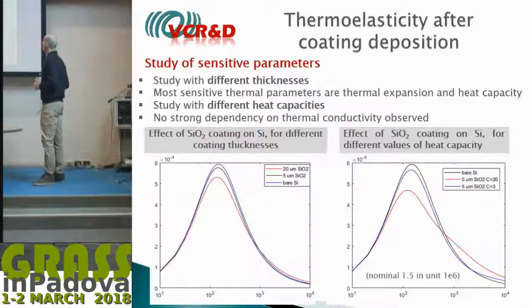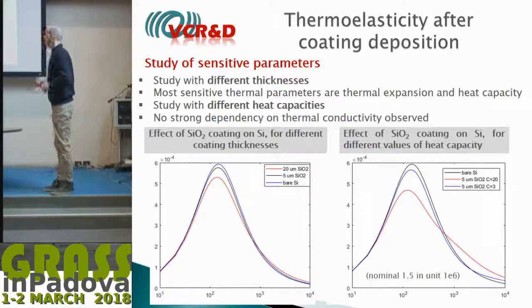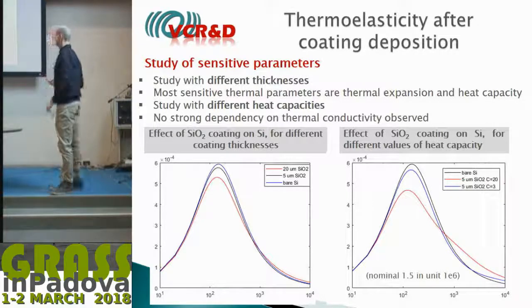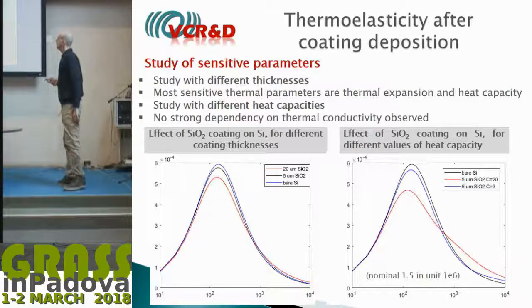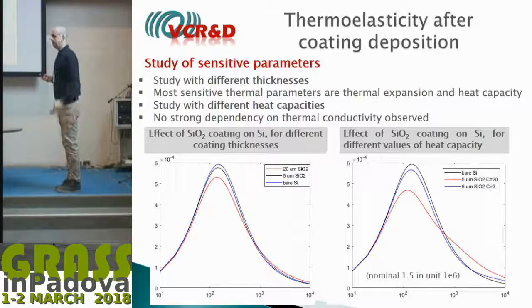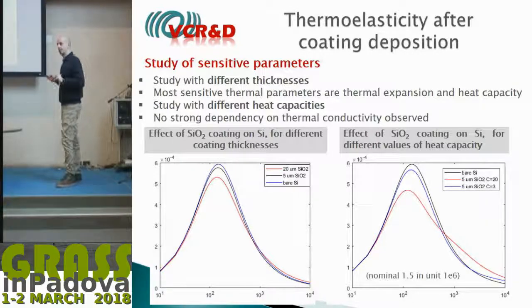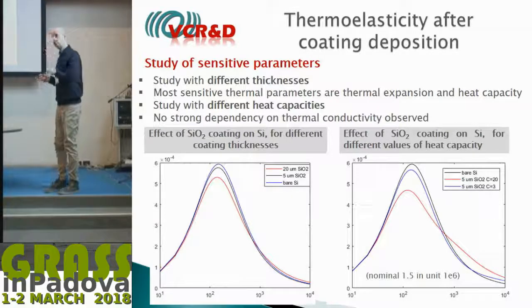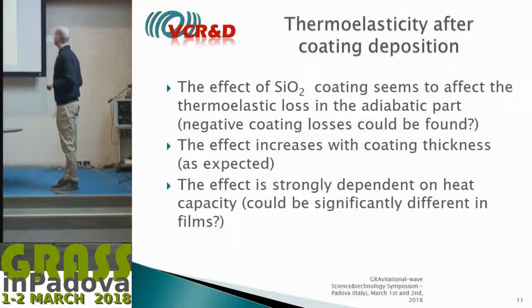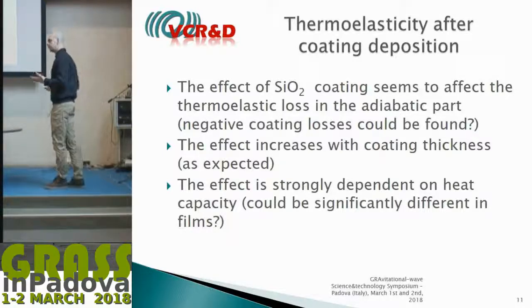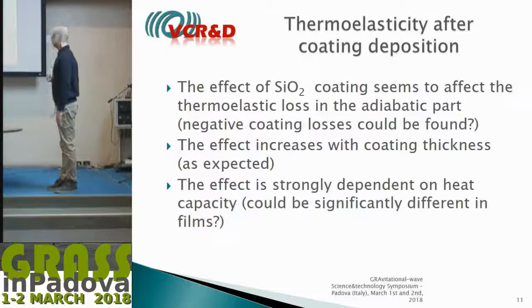So we are in the right direction. We studied which parameters impact this change in thermoelastic damping. We found, for instance, no strong dependency on thermal conductivity—which was unexpected. Of course, coating thickness has an obvious impact, but other parameters matter too. The heat capacity of the coating layer is important, though it may not be well known for thin films. The thermoelastic effect appears to be affected by the coating in the adiabatic (high-frequency) regime, with the effect increasing with coating thickness and strongly depending on heat capacity, thermal expansion, and other coating parameters.